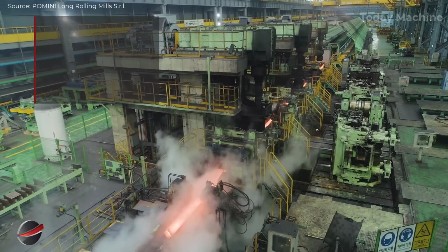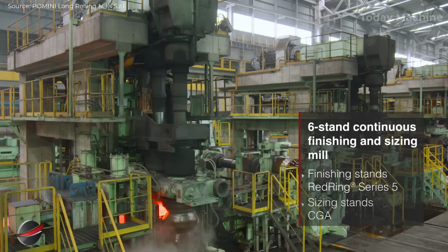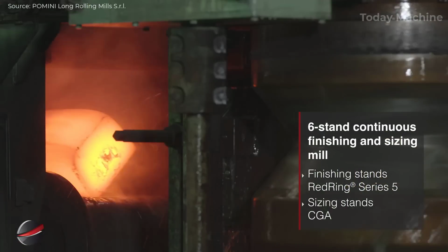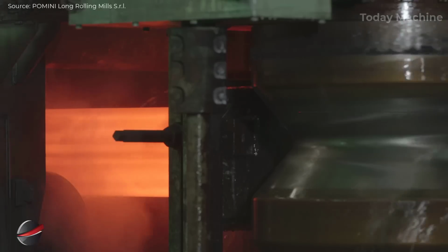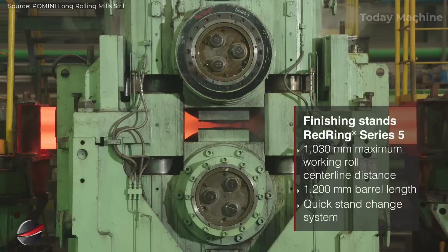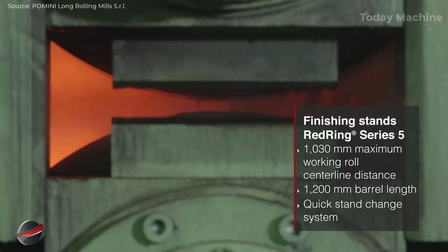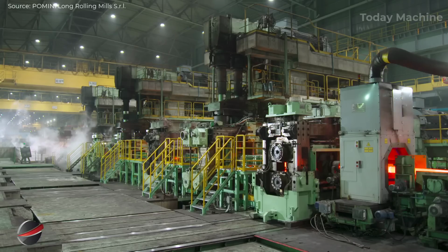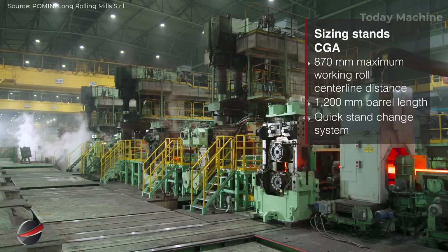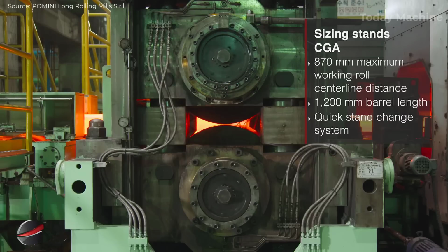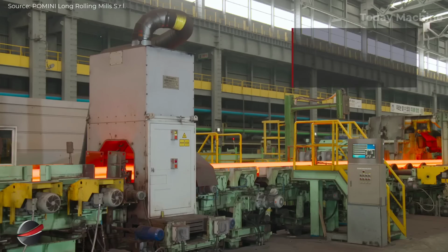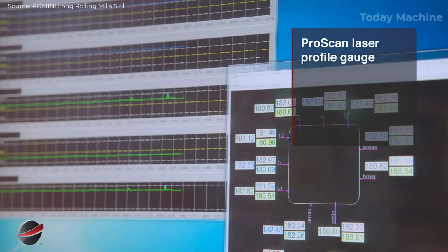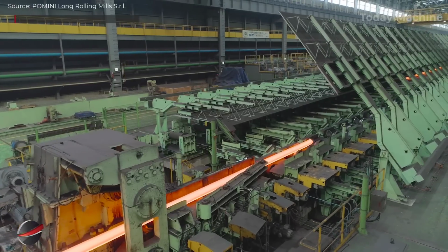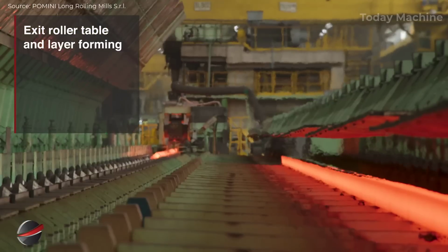The continuous mill consists of 6 stands for finishing and sizing, with Red Ring Series 5 stands for the finishing process and CGA stands for the sizing process. The stands allow for precise shaping of the bars, with working roll centerline distances of up to 1,030 millimeters for the finishing stands and 870 millimeters for the sizing stands, both featuring a barrel length of 1,200 millimeters. The mill uses a quick stand change system to minimize downtime between product changes. A ProScan laser profile gauge ensures dimensional accuracy during this stage.